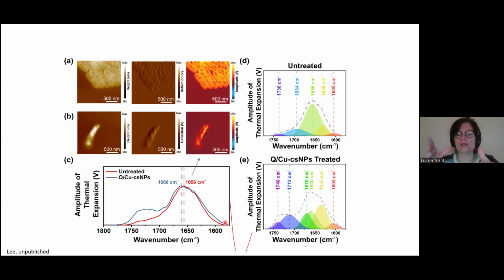But nonetheless, the data we collected showed that we can detect some chemical changes and morphological changes that are taking place in the bacteria that are exposed to different treatments. And we also did another protocol that I'm not showing here that shows that the mechanical properties of these bacteria are also changing when they're treated with those treatments.